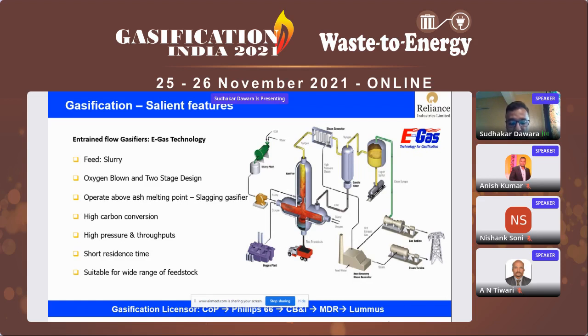And then they are converting that plant into blue hydrogen, because we have the advantage of gasification, where all the CO2 stream is available as pure CO2. So they are using that CO2 for sequestration, and they're converting the entire syngas into hydrogen, which will be used for mobility applications, and they call it blue hydrogen. It's not like gasification is going away because of these CO2 issues. We need to understand what innovation is required to continue working in the right direction.